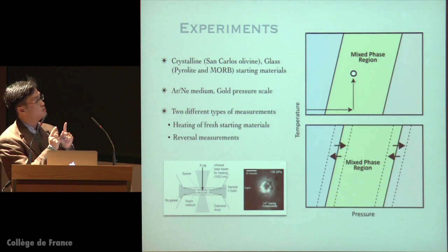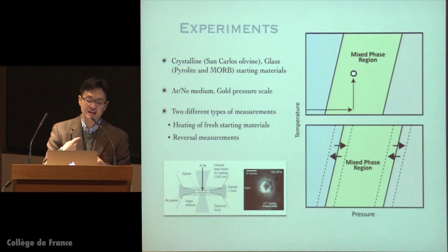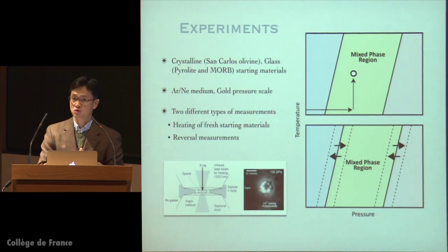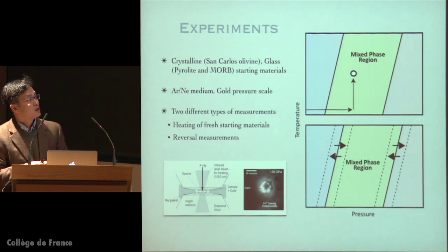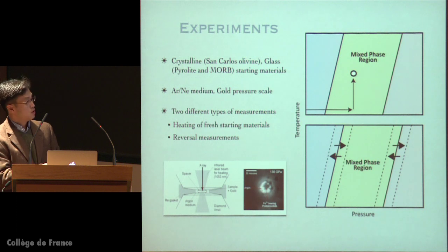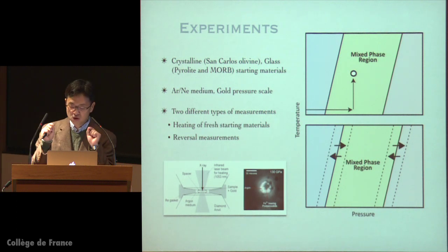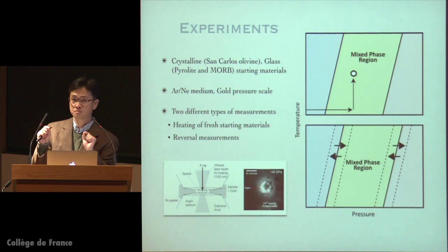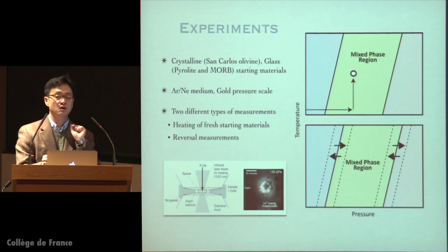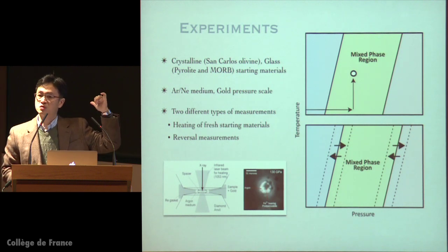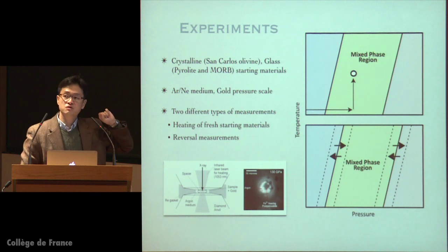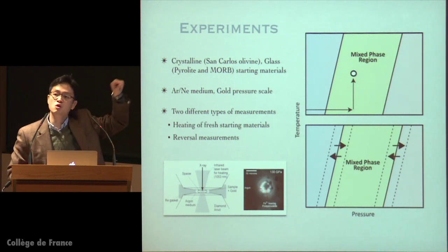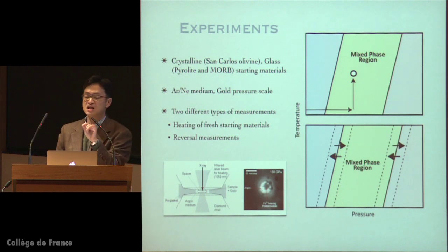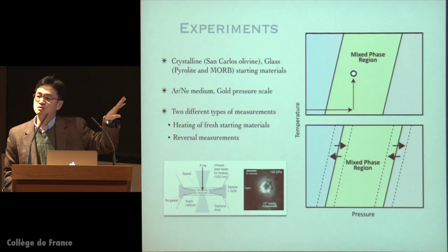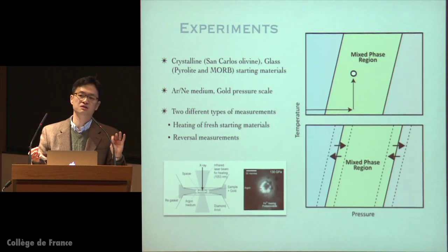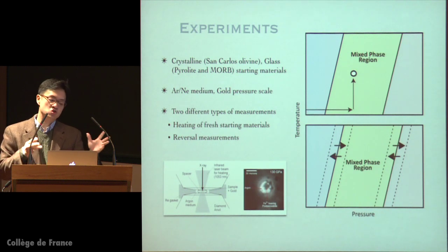And one thing I'd like to mention here, which has been a development on our side, is to use two different ways to determine the phase boundary. So in the 2009 paper, we measured the phase boundary using the traditional method in low-pressure petrology experiments, where you cross the boundary along the compressional direction and decompressional direction. So you cross the boundary from low-pressure phase to high-pressure phase, and then high-pressure phase to low-pressure phase. That gives you some idea about how much kinetic effect you would have for the phase boundary determination. So that gives you a reasonable estimate for the uncertainty of your measurements. So we thought that is the strength of the measurements.